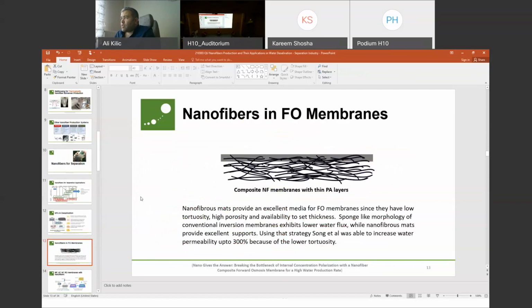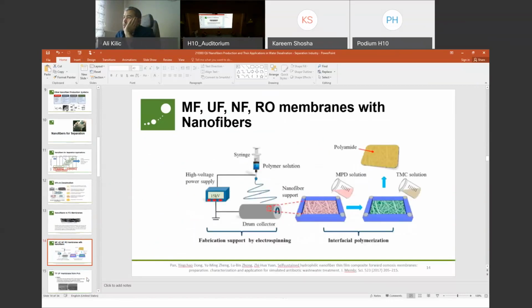There are some novel applications other than reverse osmosis membranes. So nanofibers are also doing good in this regard. They are used in some FO membranes, and for instance, in some studies, they were able to increase the water permeability, up to 300% increases can be mentioned. So here you see actually the main mechanism. We are firstly producing the nanofibers over our substrates, and after that we are making this interfacial polymerization to go for reverse osmosis, nanofiltration, and microfiltration membranes.